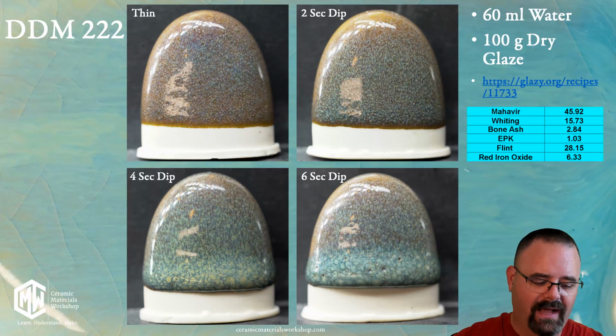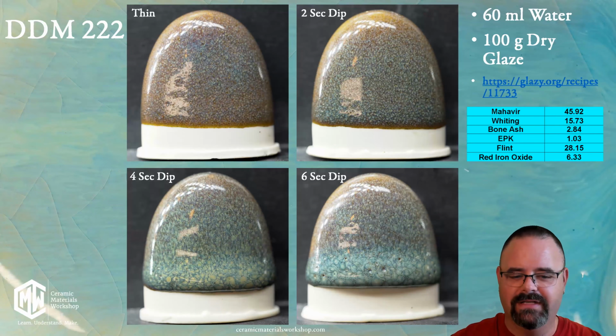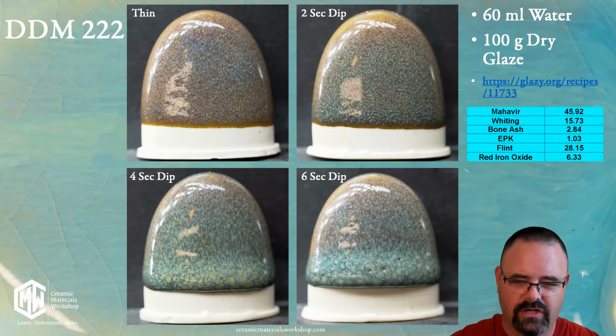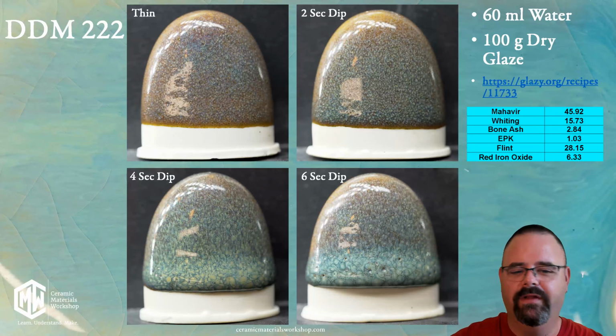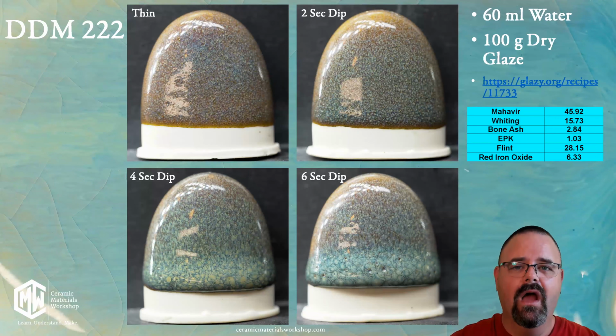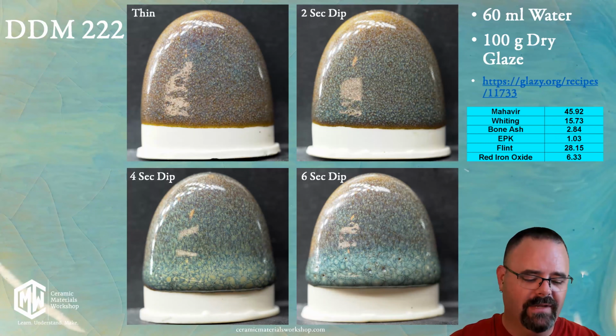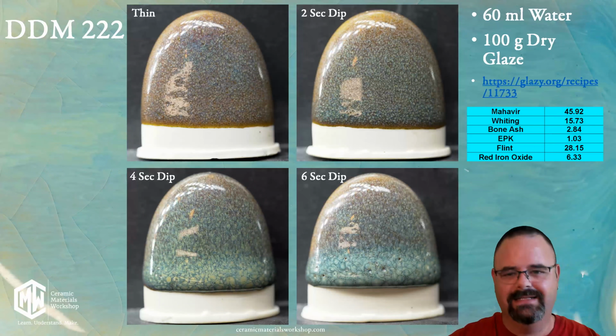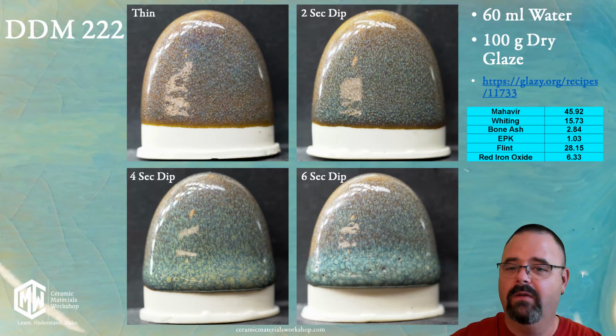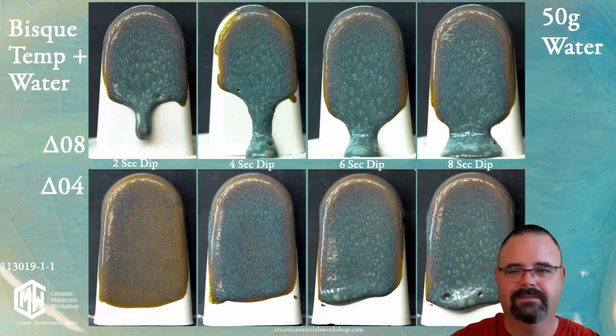Now, we can talk about why you get that at another time, but some glazes need a particular thickness to get a particular quality of glaze. And this phase-separated oil spot is no different. You have to get it just right on the thickness. It lives in a Goldilocks zone. But a couple of things to know is that I also mix this glaze with 60 milliliters of water in a 100-gram dry batch. And this is the first thing that I would advocate to you. Measure your water. I firmly believe that we should all be listing water when we are listing glaze formulas, because water content dictates how a glaze will perform. And what do I mean by that? Well, let's look at this.